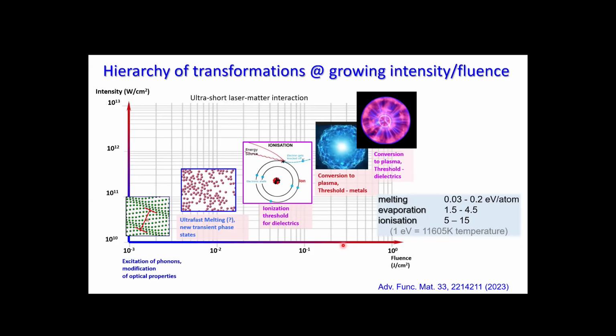A femtosecond laser desktop unit can reach, with different focusing and different pulse energies, this window of fluences. The fluence divided by pulse duration gives the intensities you work with, terawatt per square centimeter and above. So you can go from excitation and heating up of materials, which is acoustics. Nonlinear optics is actually even lower. Then you start to modify the material: you can melt, you can evaporate, you can ionize and create breakdown plasmas. Before tunneling ionization is somewhere here in this corner. So you see this range, and we can simply choose how much energy we should deliver to our samples, going through different material modifications and different phase transitions.